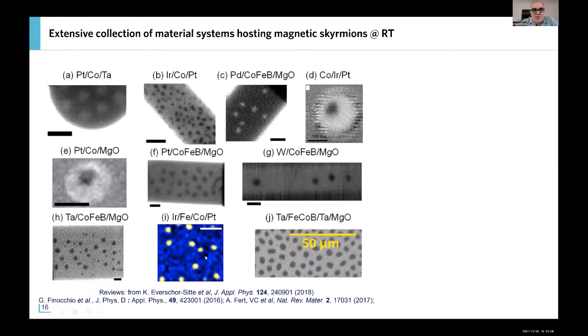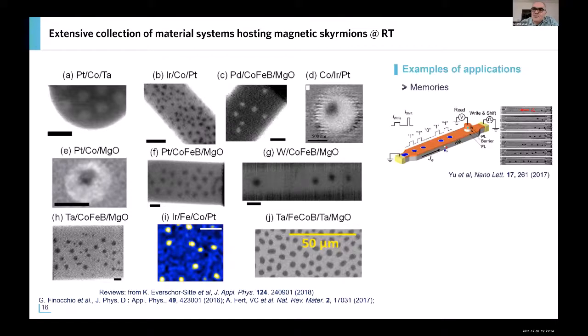And in fact, I like to show this image I took from this review paper. You see there are very different systems at room temperature with different sizes, ranging from a few tens of nanometers in diameter up to a micron or bigger, but all of them, importantly, have a fixed chirality, so they can be moved by spin orbit torque, as I said before. So in terms of application, I will not say too much today. I already mentioned this concept of racetrack memories. So you can generate Skyrmions, move the Skyrmions, and detect the Skyrmions by either a magnetoresistive effect or Hall voltage contributions. And this could really be the future for very emergent memories.